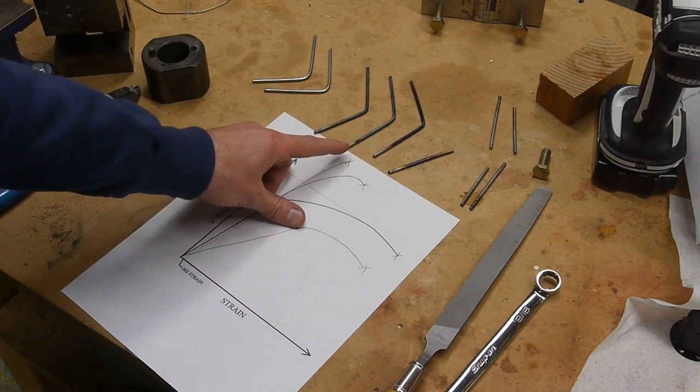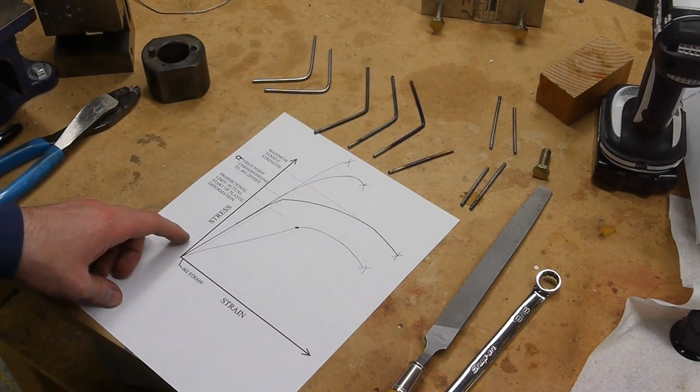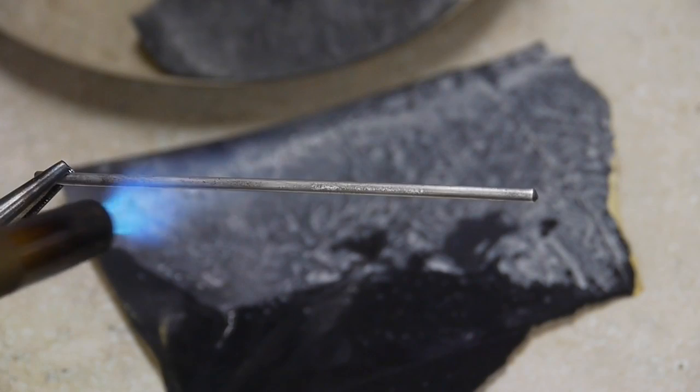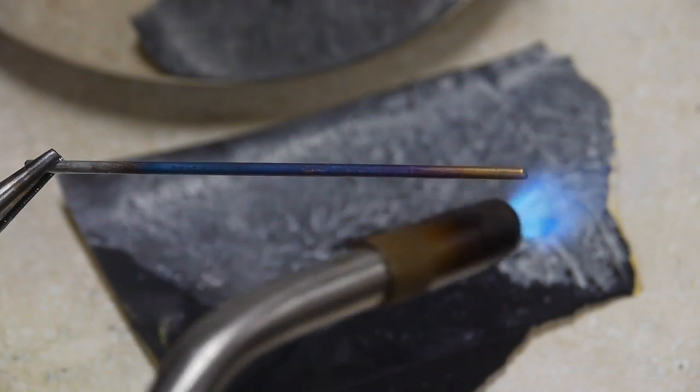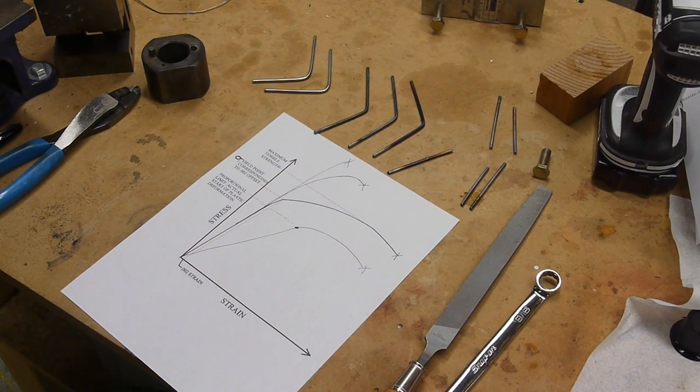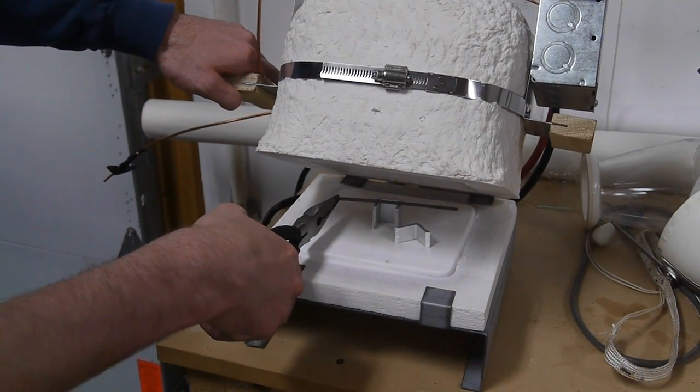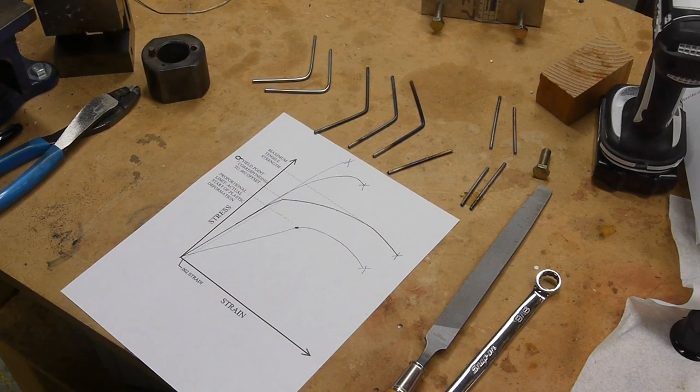Very conveniently, steel will change color in air based on how high we heat it up. The color change comes from an oxide layer that's forming on the steel and it's interfering with light. We can see what temperature the steel is based on what color we see because the oxide layer is forming an optical interference pattern there. As we heat it up, we'll see a straw yellow color and then orange and then brown and purple and then blue and then light blue. The hotter we heat it up, the more strength we give up in return for getting more toughness. There's quite a bit of research and fine tuning to be done here, but for home shop hardening and tempering, it's actually quite an effective and decent means of setting up tooling. Of course, if you have access to a kiln, it makes more sense to just set the temperature that you want to temper your steel to and put it in the kiln and leave it for the prescribed time, which is actually like an hour or two usually, and then take it out of the kiln and let it cool down.